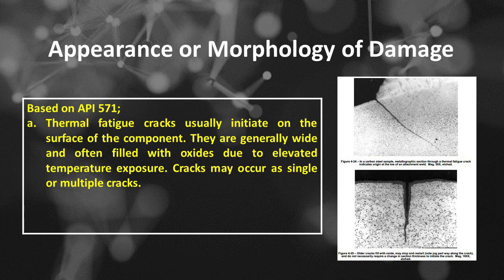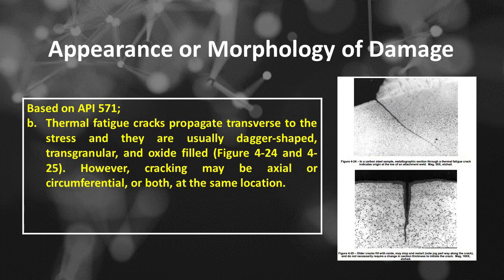Appearance or morphology of thermal fatigue damage. Based on API 571. The first is thermal fatigue. Cracks usually initiate on the surface of the component. They are generally wide and often filled with oxides due to elevated temperature exposure. Cracks may occur as single or multiple cracks. The second is thermal fatigue. Cracks propagate transverse to the stress and they are usually dagger-shaped, transgranular, and oxide-filled, see Figure 4-24 and 4-25. However, cracking may be axial or circumferential, or both, at the same location.